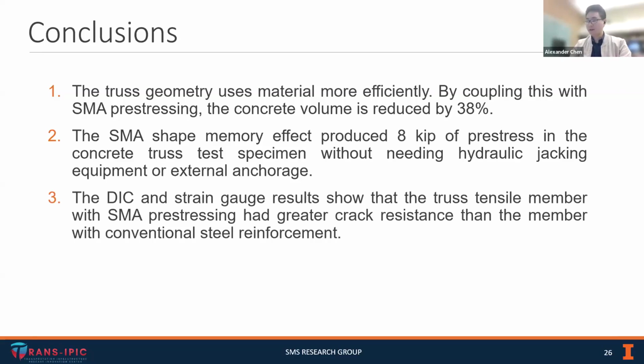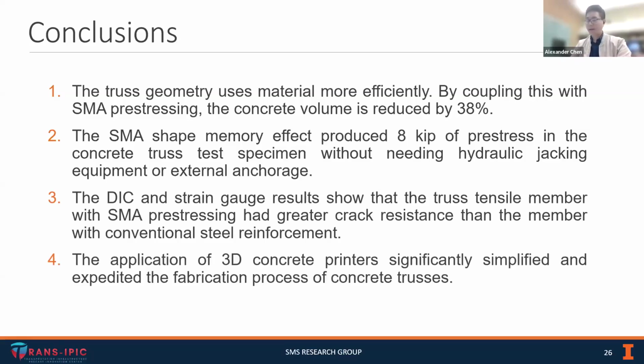The DIC and strain gauge results show that the truss tensile specimen with SMA pre-stressing had greater crack resistance than the truss tensile member that was using just conventional steel reinforcement. And lastly, by using 3D concrete printers, we can greatly speed up the fabrication process of these concrete trusses.